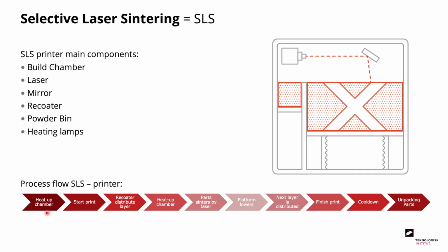Taking a look at the process flow for SLS, there's much more than just the printing in it. First of all, you have to heat up the build chamber to just below the sintering temperature. Then you have the printing. Between each layer you do this recoating. As mentioned, typically 0.1 millimeter layer thickness. When you've deposited a layer and sintered it together, you lower the build platform and then deposit another layer. Heat it up again, sinter it.